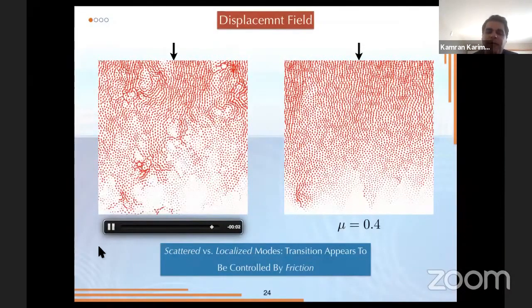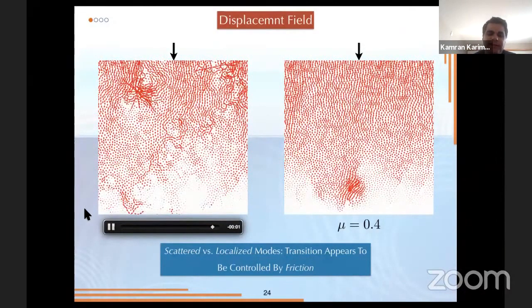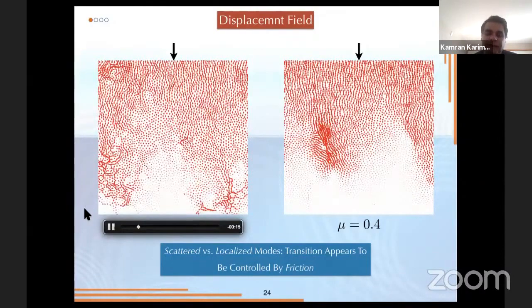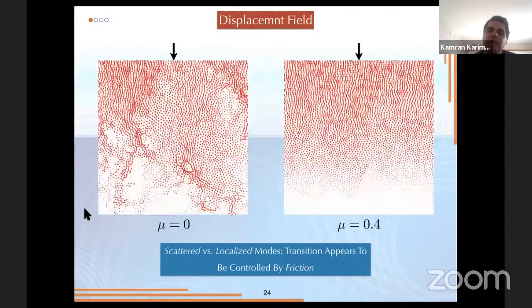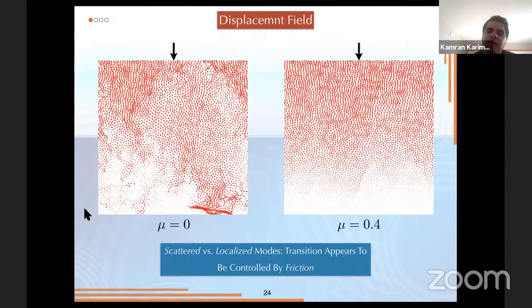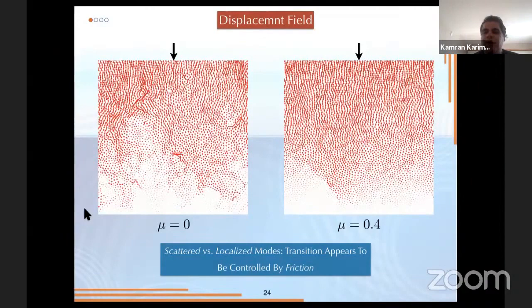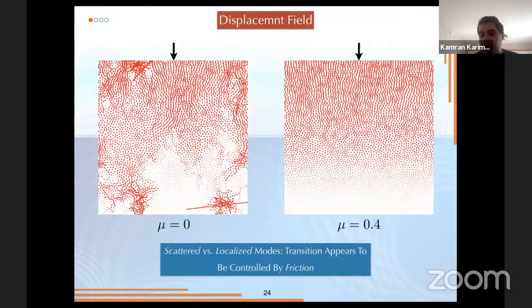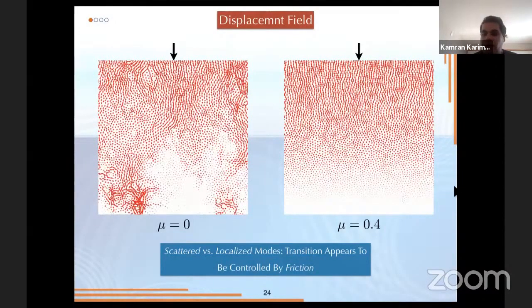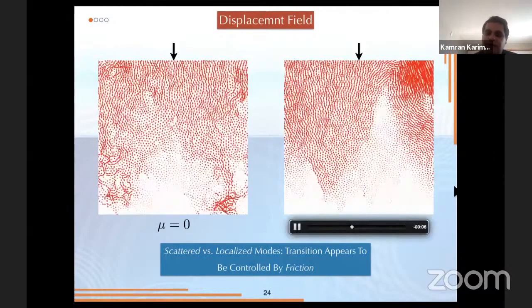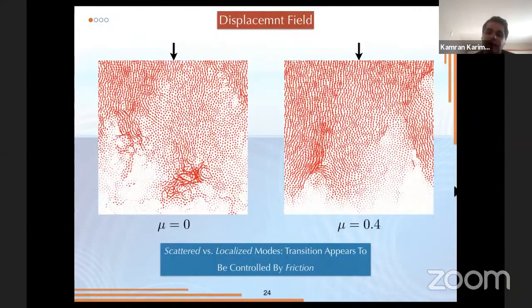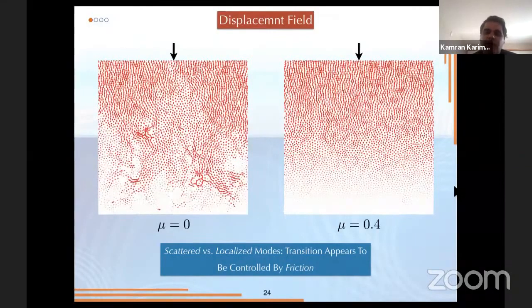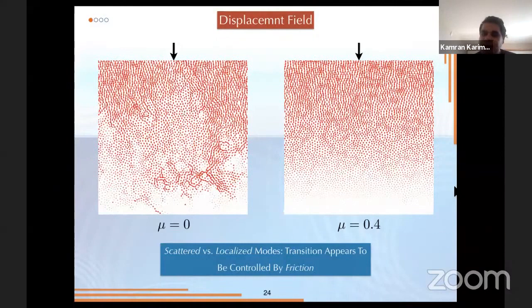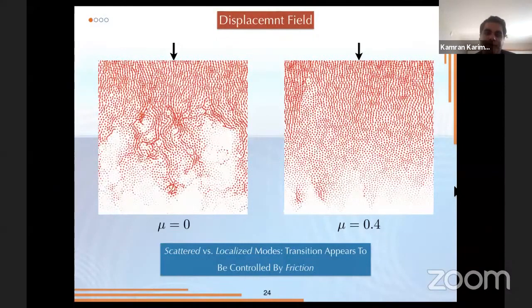On the left, which is associated with the frictionless system, you can see that events are really scattered, almost homogeneous all over the space, and they're quite short range. And on the right, for the frictional system, they're more like crack-like extended features that are quite localized in space. So this transition seems to be controlled by the local friction coefficient.